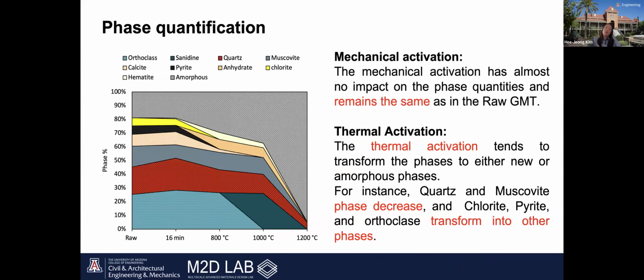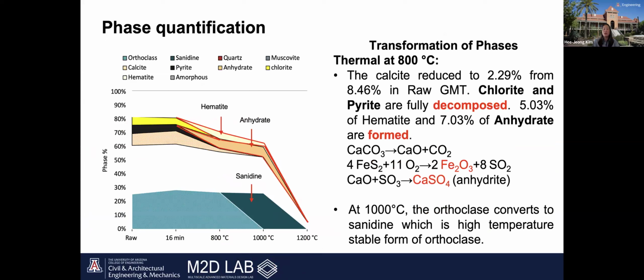So it is important to know how much of each phase is present before and after the activation, because this can be related to their activity. And to measure this, we use the Rietveld refinement for phase quantification.